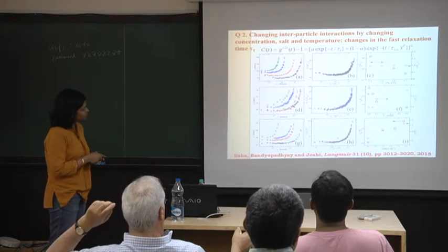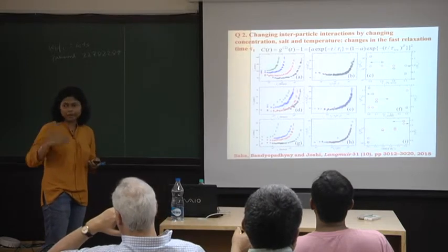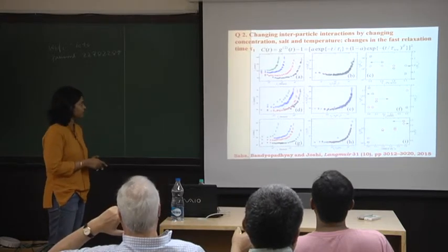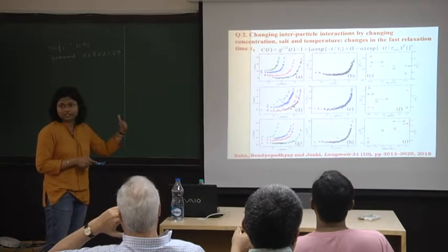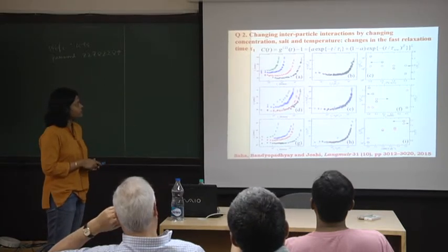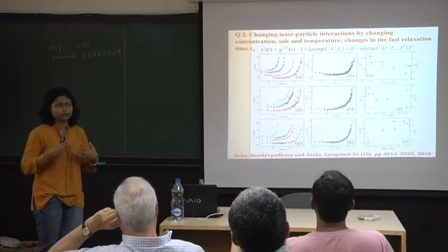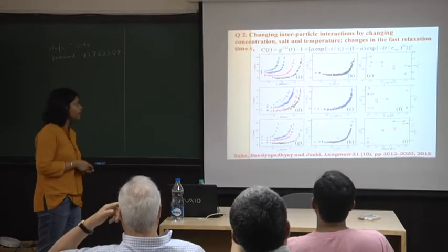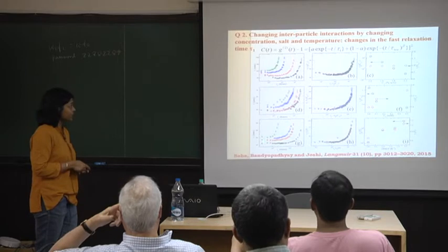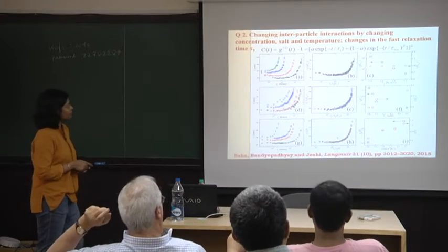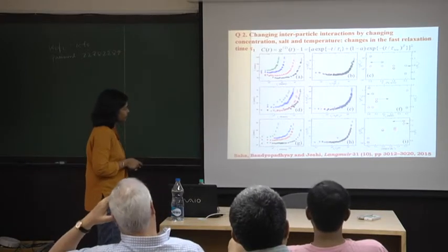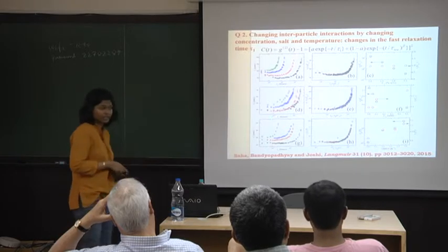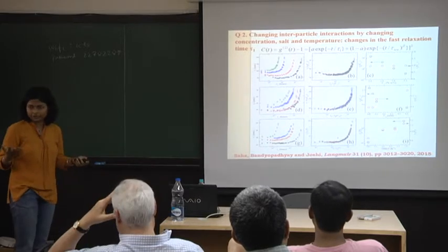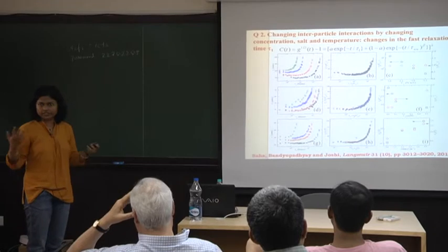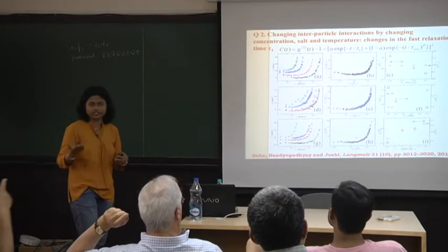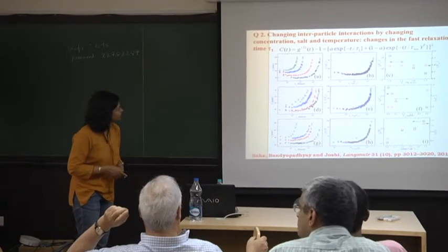In the first sample that you see here, we've only changed the particle concentration of the Laponite particles, keeping the salt concentration as well as the temperature constant. In this case, we've changed the salt concentration, keeping the particle concentration of the clay and the temperature constant. In this case, we've changed the temperature. Okay? So this is with concentration increasing, salt increasing, temperature increasing, and you can see that increasing the temperature, at least qualitatively, looks rather similar to increasing the salt, which is, sorry?